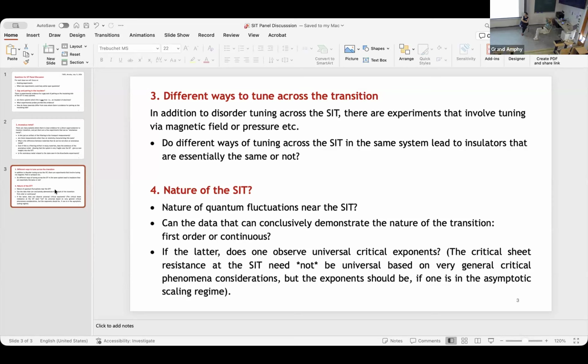Yeah. But they're done in a very controlled, beautiful way, far from this transition. But surprisingly, they work up to one quantum of resistance. Maybe so, but you're already pushing them beyond the regime of validity, and the transition itself is definitely outside. Well, at the transition itself, you get the other quantum corrections that come from superconducting fluctuations, and altogether it makes a very consistent picture. Which algorithm is that? With localization and interaction. The logarithmic increase in temperature that you have always.